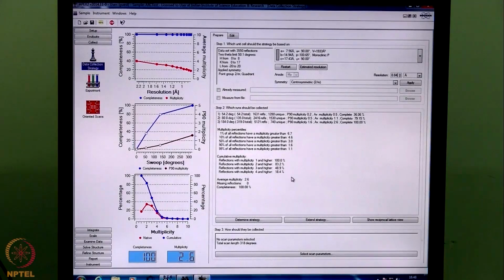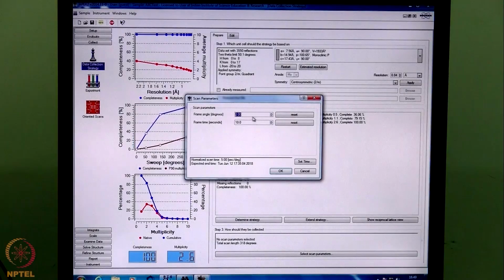So now it shows that here we have 3 sets of runs. In the first set, it will give us a completeness of 26%. Second set will give us a completeness of 80%, and third set will give us a 100% completeness. So now we need to decide on the time, that is the exposure time for data collection, and the frame width. Normally we collect data with frame width of 0.3 degree and a 10-second exposure time. That means every frame will be measured for 10 seconds.